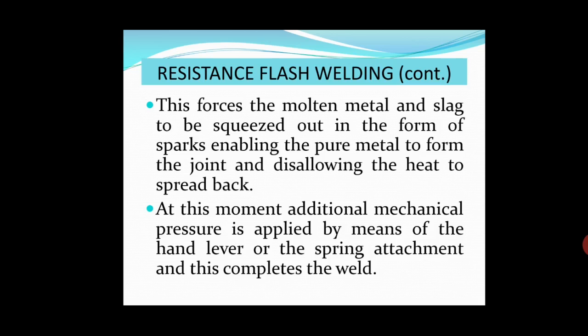Two things: because of this flash or squeezing out of molten metal and slag, pure metals come in contact and form the joint, and this disallows the heat to spread back. So the heat affected area becomes less. At this moment, additional mechanical pressure is applied by means of the hand lever or the spring attachment, and this completes the weld.